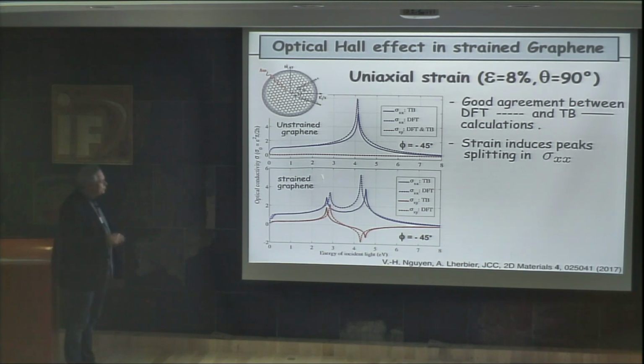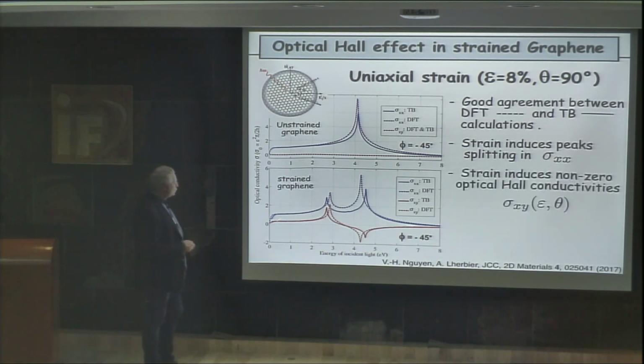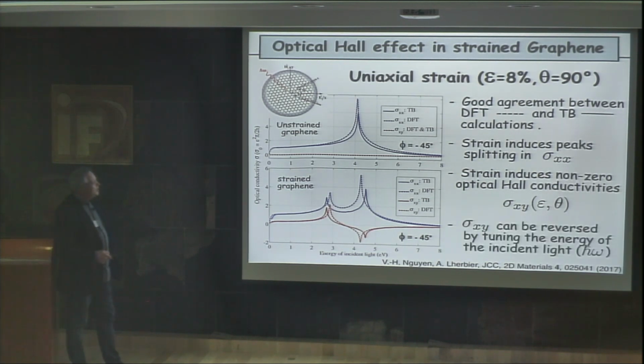After that, we impose a certain strain. In this case, it's 8%, and it's a certain direction for the strain. It doesn't matter. And what you see is the strain induces some peak splitting in the sigma XX, so in the optical conductivity. And this is quite interesting. And also, strain induces non-zero value for the optical Hall conductivity in your system. So it's no more zero, it's clearly positive and negative here. So you clearly have the possibility of tuning the optical Hall conductivity from positive value to negative value, depending on the energy of the incident light. So you clearly see that it's a quite interesting system because it will depend on the energy of the incident light.